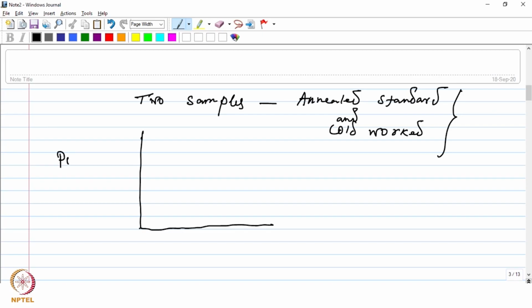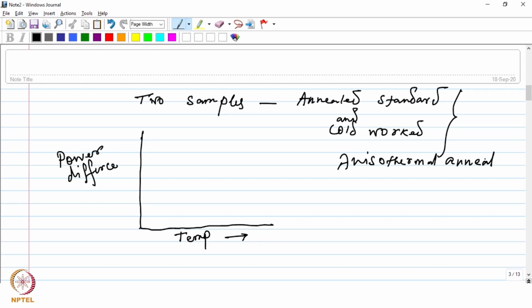So as I said, there will be a power difference. The power needed to heat these two materials, one the standard annealed sample and the cold worked sample, there will be a difference in that. So that can be plotted against the temperature, as you continuously heat it. So this is not isothermal, this is anisothermal heating. So as you anisothermally anneal these two materials, and capture the power required to heat these two samples, you can generate a plot like this.